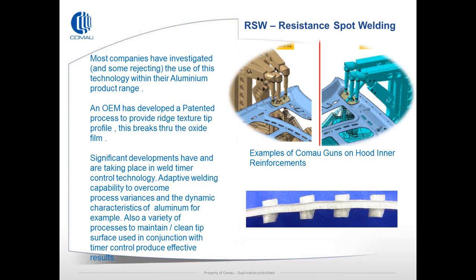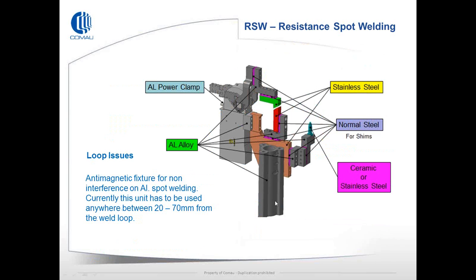But there have also been a wide range of significant developments within the weld timer controls technology. Adaptive welding capability to overcome variance is giving very good results in the marketplace. A variety of processes to maintain and clean the tip surface in conjunction with the timer can also produce effective results. Here we've got a 3T stack-up of an aluminium joint, approximately 2 mm material, so totaling approximately 6 mm, giving a robust joining process.